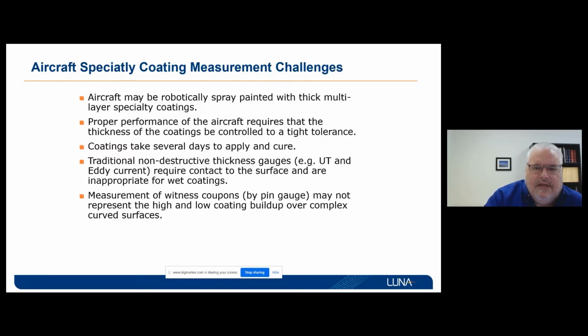One of the first applications I'm going to talk about is the measurement of the thickness of aircraft coatings, and particularly specialty coatings, which are often very, very thick. They may be from 20 thousandths of an inch thick up to 250 thousandths of an inch thick, getting into the centimeter range. And you have to have pretty tight tolerance to the thickness. In many cases, the coating applications take several days to apply and cure.